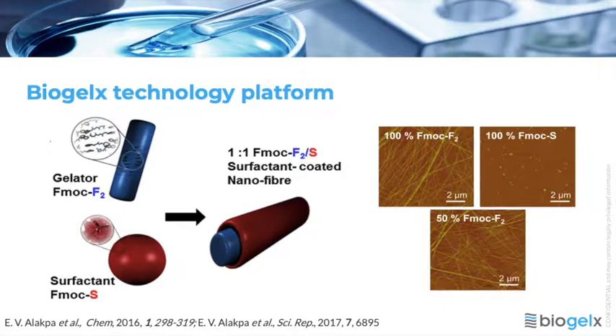Now, when you mix these both together in deionised water to make what we term our pre-gel, we get this nice fibrous structure that we'd seen previously with the diphenylalanine, but in this instance, due to the FMOC group, the FMOC-S can co-assemble with this structure to coat this fibre with the polar groups from the side chain and the free C terminus of the FMOC serine. And this is quite important for cell culture applications because it means that these fibres then have a polar surface to which the cells can attach.